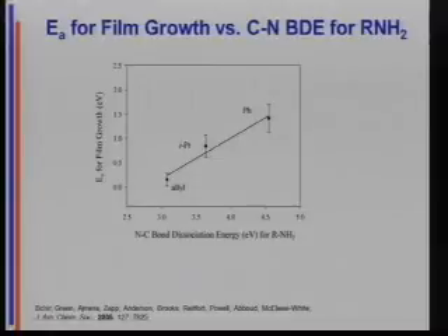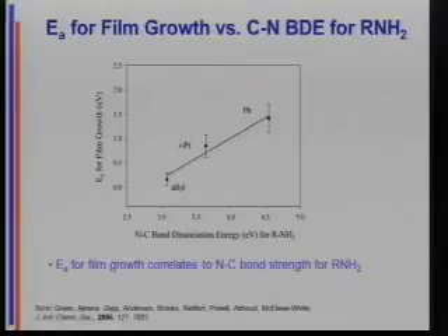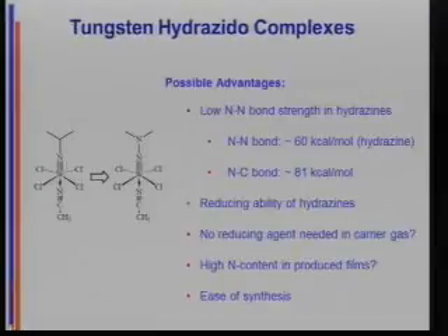Okay? Now, you remember that my low temperature growth there was 450, and that's really too high. I'd like to take it down. So I can drop the activation energy for film growth by changing the bond dissociation energy of that bond. Okay, so how do I do that? Well, let's go from N-carbon to N-N, because a nitrogen-nitrogen bond in a hydrazine is about 20 kcal less than a CN bond in an amine. So what I've done is I've knocked back my activation energy for that cleavage. And there are some other advantages here, but let's just talk about temperature for a while.